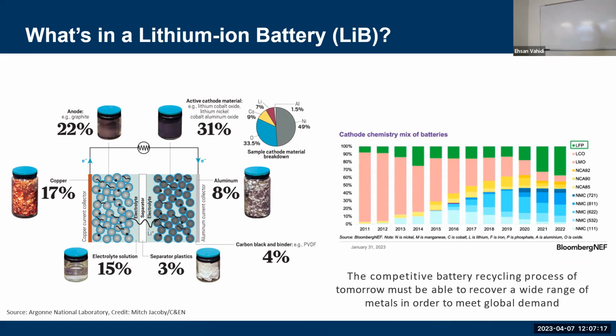And then the cathode material, which has been a lot of the focus of the recycling industry because it's the most valuable component. This is where you have your lithiated metal oxides, and that is then attached to an aluminum current collector, which current is facilitated by using carbon black and a fluorinated binder. Now to keep the battery from shorting out, we have a separator, and then also the electrolyte, which comprises about 15% of the battery, also contains lithium salts to facilitate the transfer of lithium from anode to cathode for charging and discharging cycles.